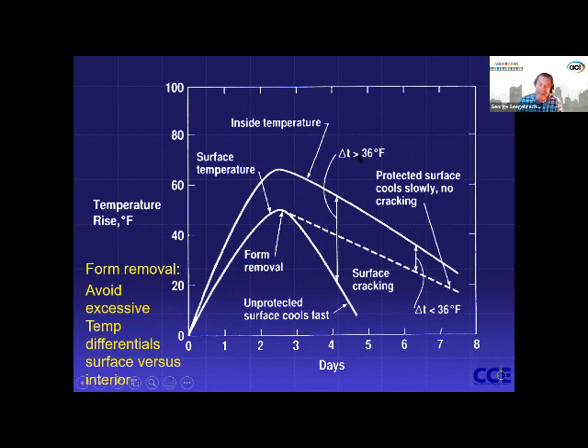Once you take the forms off, now we've got greater and greater, and the rule of thumb is you want to be less than a 35, 36 degree temperature differential. And that is a rule of thumb. As you have this heat of hydration, you're actually delivering maturity to your concrete, and that heat helps develop its strength. So as that time and temperature advance, the 36 degrees becomes, you can move past that and go to greater and greater temperature differentials that the concrete can tolerate without cracking. But that again depends on the ambient temperature that you're cooling it to on that form release, what the mix design is, and so on.